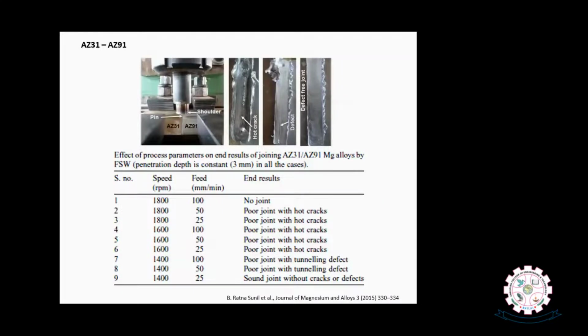The main processing parameters that we observed in friction stir welding, two important process parameters, are tool rotational speed and tool feed, in addition to other minor influencing process parameters. Among them, with higher speed, the generation of heat will be higher because of the friction between the tool surface and the workpiece, and also friction between the pin surface and the rotating workpiece material. If the feed rate is lower, the heat concentration will be higher in the processed zone. Therefore, higher tool speeds and lower feed rates usually result in more heat concentration in the weld zone, which may yield defects as well as grain growth. If defects are not present, grain growth.